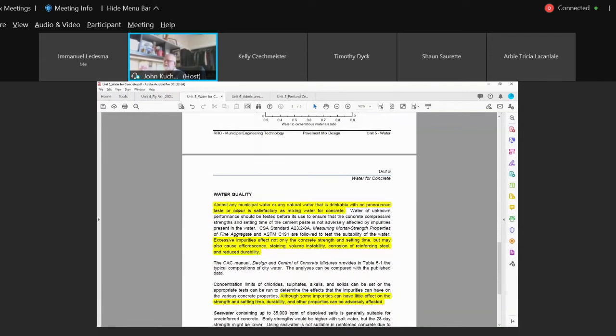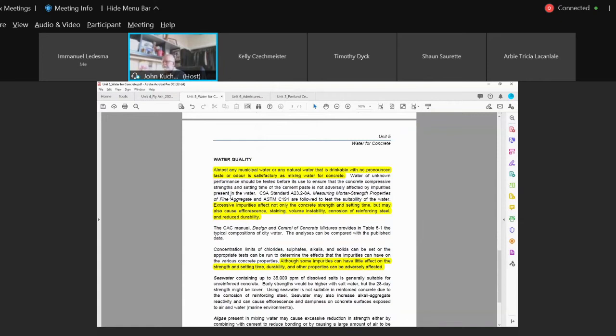Water quality. Almost any municipal water or any natural water that is drinkable with no pronounced taste or odor is satisfactory for mixing water. And there's certain criteria. When you test that water from a northern remote site, you're going to actually use the cement that you're going to be using, and you're going to make cubes with this water, and you're going to make cubes with standard control water, let's say water from your faucet. And the strength has to be a certain ratio between the water that's in question versus the standard cubes, okay? And that's one way that they're determining, yes, from strength, that water will give us the strength.